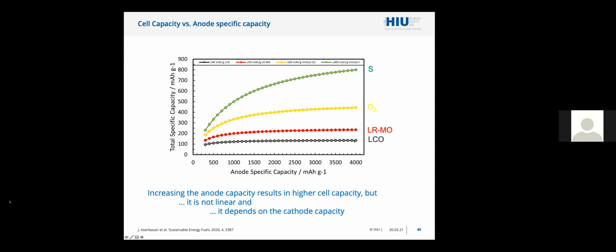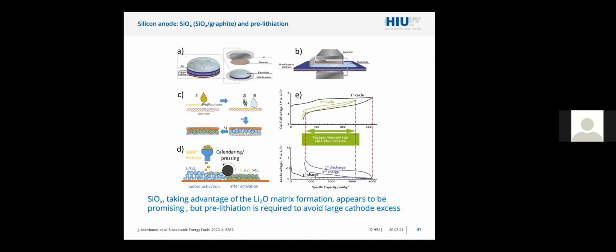So increasing a little bit the capacity of the anode is definitely good already, for example, for the lithium rich or lithium and manganese rich oxide cathodes. But we don't really need to go very high. Silicon oxide by itself or in combination with graphite in composites is definitely an interesting material. Because it takes advantage of the lithium oxide matrix, which is formed during the first lithiation, it's extremely interesting actually for commercial cells.